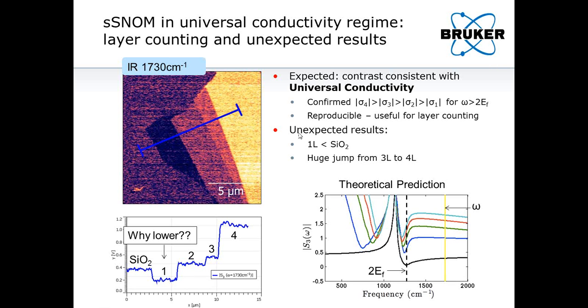And the unexpected aspect of this image is that they're twofold. Basically, the first layer is lower than the SiO2. That was an unexpected result. And there was also this huge jump from the 3-layer to the 4-layer, which we also did not expect.